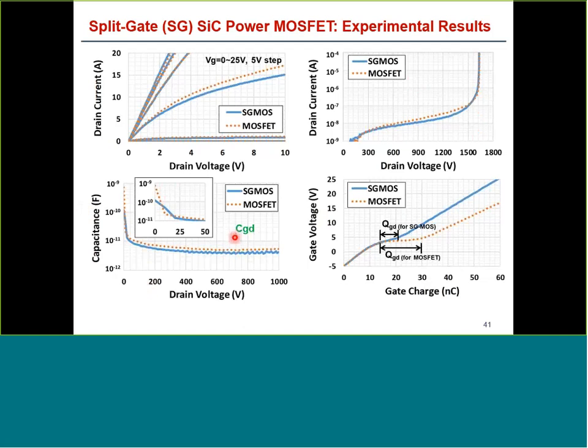So this is the CGD that I'm showing you in this chart. And usually CGD is given at 1,000 volts, and at 1,000 volts there is a small improvement. But what you have to note is that at small drain biases, there is a very large improvement, almost 1 order of magnitude reduction in CGD. And this is what translates to a much smaller QGD for the split gate devices.